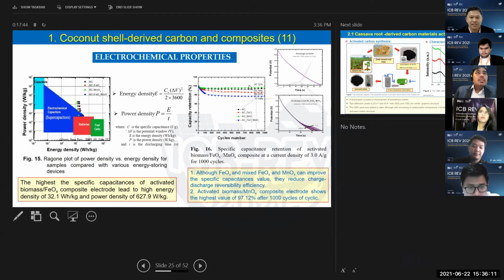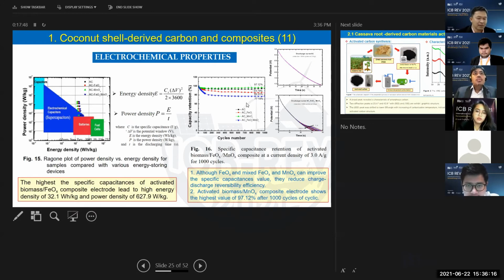Unfortunately, for the capacity retention study, as you can see from this figure, most of the materials prepared show not so good capacity retention. But for the carbon, it's very good. Only the activated carbon composite with the manganese oxide shows a very good capacity retention. So I think in the next step, we would like to improve this property so that the material can show a better capacity retention.